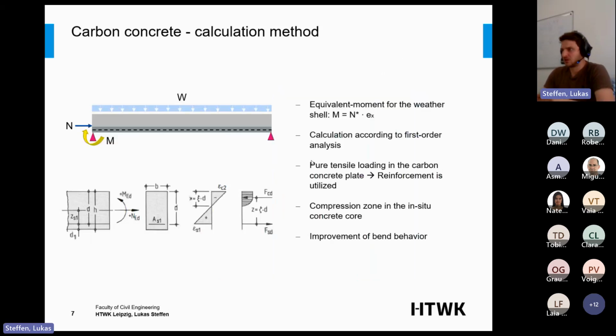That's not an issue. We can calculate it really simply according to first order analysis. We only have to apply an external moment for the weather shell. It's simply the dead load times the spacing between the two shells. And there we only have compression in the in situ core and only tension in the carbon concrete panel. So therefore the carbon reinforcement is fully utilized.